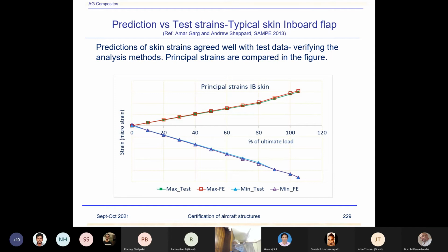And after testing, our engineers went again to modeling, tried to investigate, looked into fastener details, the elements, element types, thickness changes, all those, tweaking the figures in the analysis to match the test data. So initial analysis probably would have taken, say, 6 months, or less than that, of course. And then after test, several months were required again to match the test data. It was not an easy task, but one has to do it to show the compliance for the certification. And this takes a lot of time.